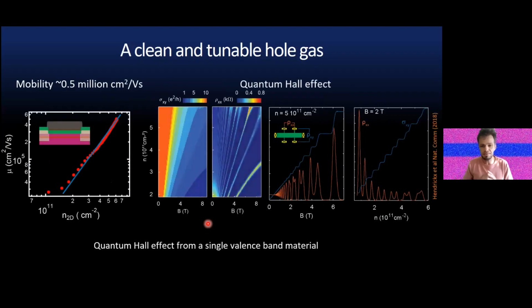Now let's see if we actually, from an electrical perspective, fulfill all the promise and the nice properties I put forward a few minutes ago. So we see we have strain, but what about the quality of the hole gas? These were really our first results where things were not really optimal, but still they were very good. In fact, we got a mobility of 500,000. Again, if you take this as an indicator of quality.